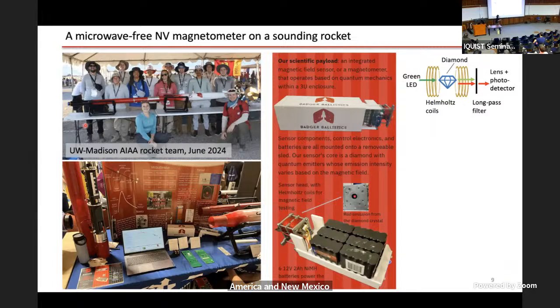Inside the rocket, we have a scientific payload that's part of the competition, where it's 3U. So what that means, each U is a CubeSat, so it's 10 centimeters by 10 centimeters by 10 centimeters. And we package a diamond that's rich in NV centers, and we use a green LED to excite these diamonds. And so what comes out will be red light. And then we filter out the green LED through a long pass filter and just directly stick a lens and photodetectors. It's the simplest way we could actually package an NV magnetometer.